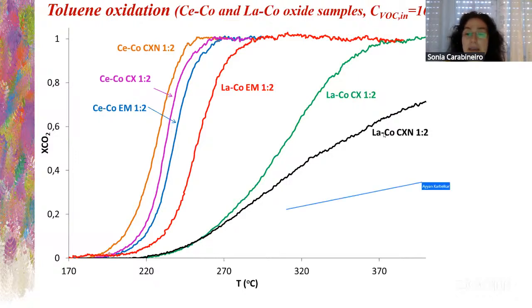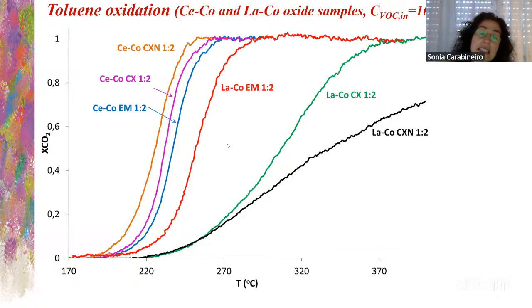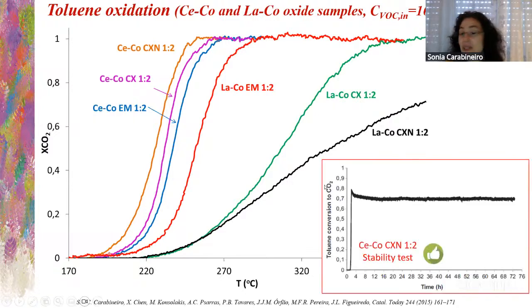So we have here samples prepared with carbon gel. This is the normal gel. This is the gel with larger pores. So we see that the evaporation method is better than this one here, for the lanthanum. But here for the cerium cobalt, the gel with larger pores was best. So here it was the opposite. So that's interesting to see these different results. So we did a stability test of the sample with the best catalytic activity, and it was quite good, up to 75 hours. Okay, so interesting.